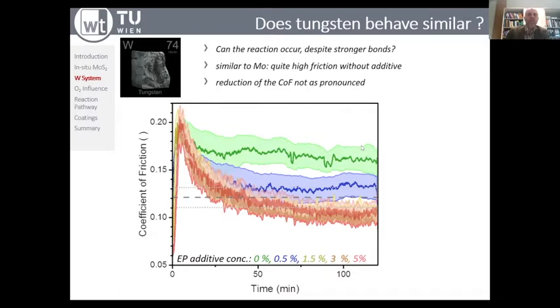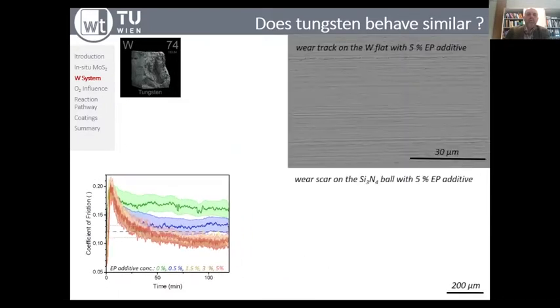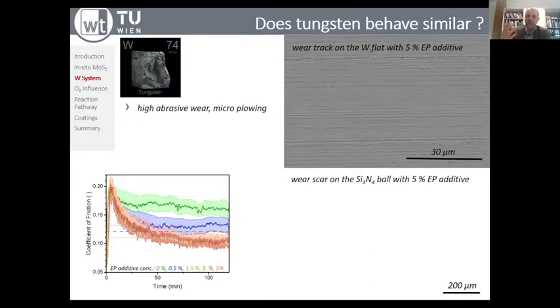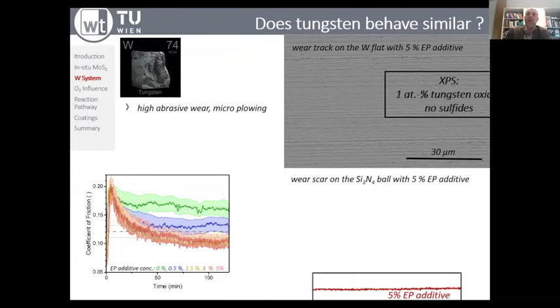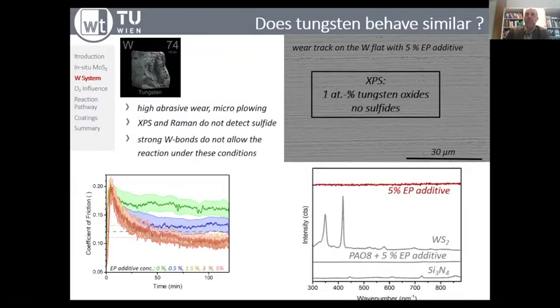What is happening there? When we go a little further and study the wear tracks, we can see that we have high abrasive wear. There are micro-plowing marks that you can identify. When you do the XPS, the amount of tungsten oxides is rather small. Compared to the molybdenum side, where we had a large amount of metal oxides identified in XPS, for the tungsten system there is only a small amount of tungsten oxides present, and there is no evidence of sulfides in the contact. So obviously something does not work properly. The question is now why? When you look at the Raman spectra, this again shows very clearly that for the 5% EP additive, you don't see any peaks characteristic of WS2.